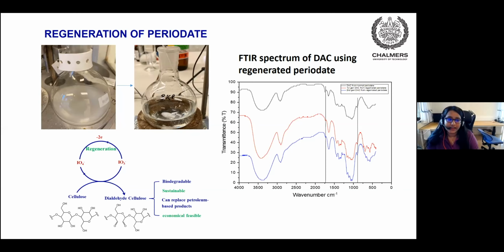This has been tried in the lab about 3 times, and we successfully produced dialdehyde cellulose from cellulose. In the FTIR spectrum, you can see a peak at 1732 cm⁻¹, which shows that dialdehyde cellulose has been formed from cellulose. The dialdehyde cellulose formed with the regenerated periodate had a degree of oxidation of 30%. This could also be tuned, since factors like time and temperature of oxidation affect the degree of oxidation, so that this DAC can be used both for Billerud Korsnäs and for Tetra Pak. We can form and modify it according to the needs of the company or the industry. Next slide, please.